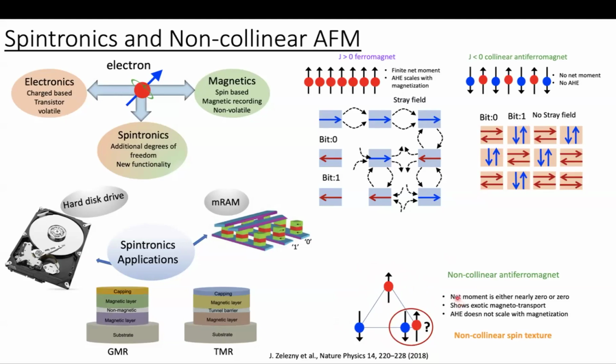But in this kind of system, because of this non-collinear spin configuration, it generates a finite Berry phase, which gives rise to exotic magnetotransport properties like large anomalous Hall effect, magneto-optical Kerr effect, and large Nernst effect, similar to the ferromagnet. So it's a combination of ferromagnet and collinear antiferromagnet. One can think that way. In terms of magnetization, it behaves as a collinear antiferromagnet, whereas in terms of properties, it behaves as a ferromagnet. But one can distinguish clearly between ferromagnet and non-collinear antiferromagnet.